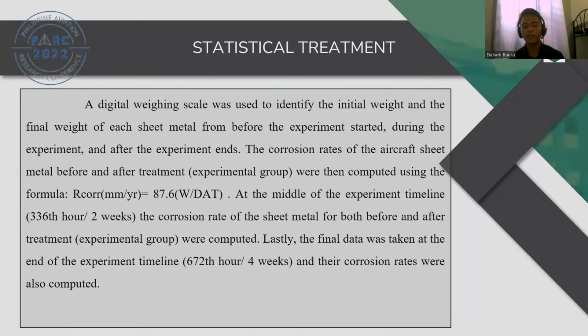So the data that we will be gathering are the weights of the aircraft sheet metal before, during, and after the experiment. A digital weighing scale was used to identify the initial and the final weight of each aircraft sheet metal. The corrosion rates of aircraft sheet metal before and after treatment were then computed using the formula R corrosion = 87.6 (which is a constant) times W for weight loss over D for density, A for area, and T for time. At the middle of the experiment timeline, which is 336 hours, the corrosion rates of sheet metal from before and after treatment were also computed. And lastly, the final data was taken at the end of the experiment timeline, which is at 672 hours, and their corrosion rates were also computed.